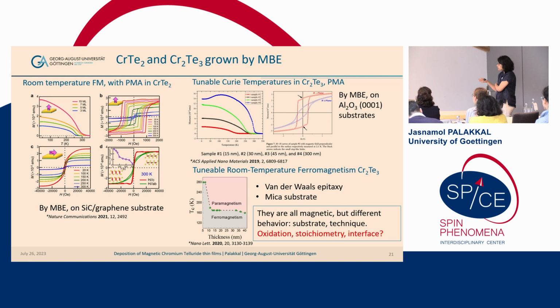And here I would like to stress again, when you investigate magnetism in a material, it's extremely important to check if the oxidation state of the cation is what you are expecting from the lattice, if the stoichiometry is correct, and if you have any interface effect. Otherwise, there could be a lot of reasons why the magnetism is originating, especially since most of the dirt that we have in the air or flying around is magnetic. It contains iron or iron oxide, and it is magnetic. And even when we take the thin film by using a metallic tweezer, sometimes we get magnetism just because we used the metallic tweezer.